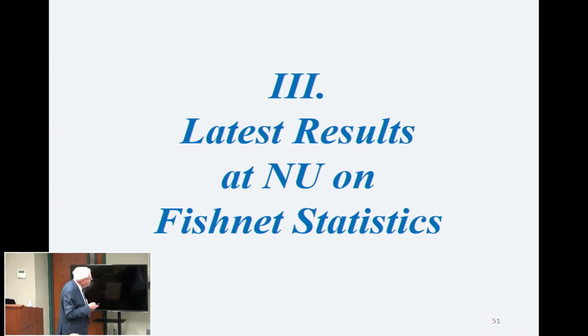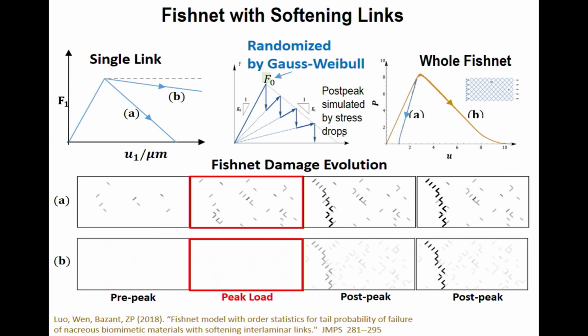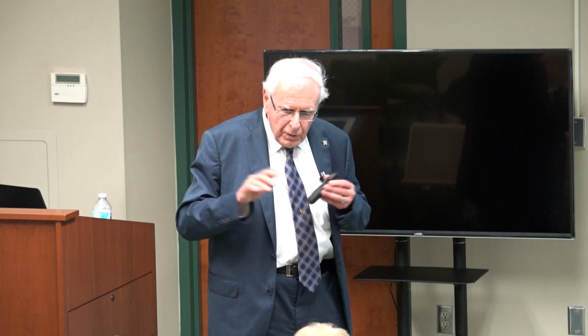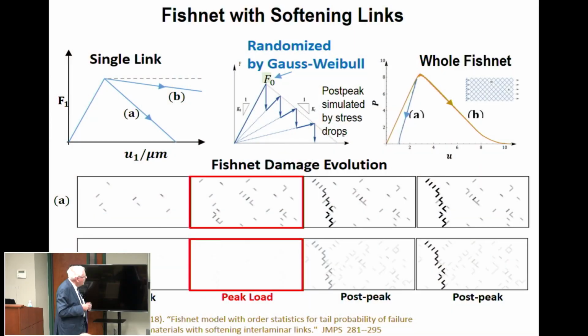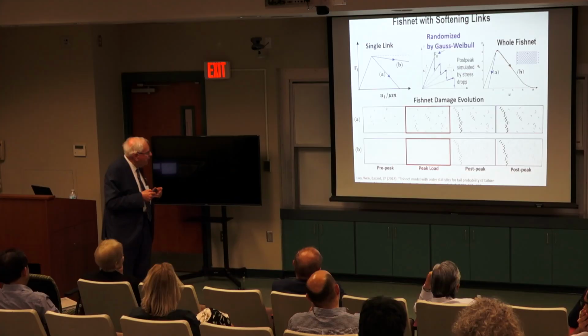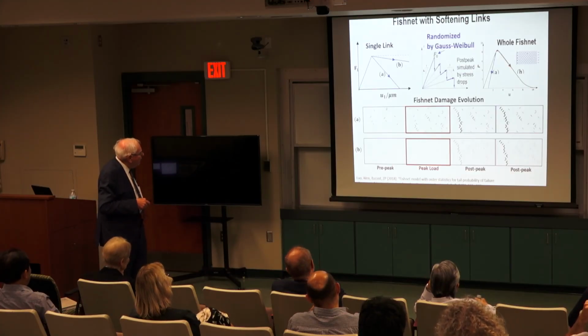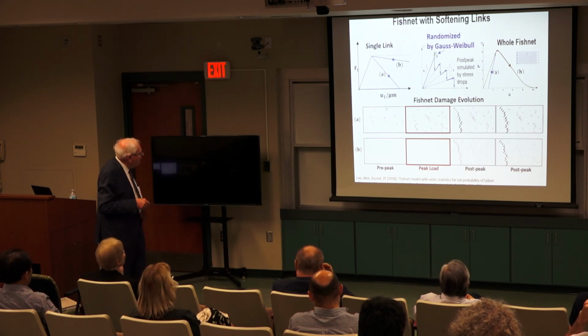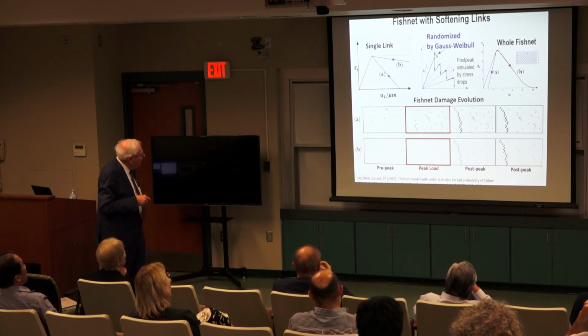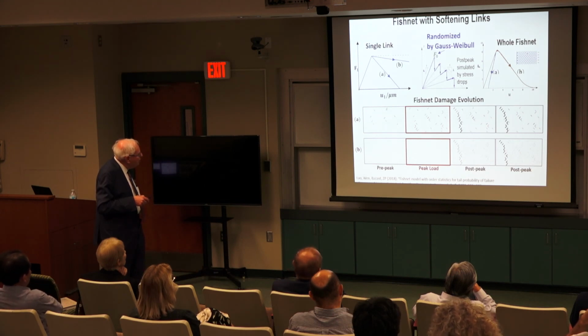Now some latest results over the last 4 months. Actually, a paper just appeared on this. Another question is, if we have this staggered platelets arrangement, I assume that the bond between these two fails as soon as the crack forms and it runs dynamically through the length of the connection between the two platelets through the biopolymer. But that's not clear. It may work in a cohesive way, that you propagate a long crack and then it becomes dynamic. And if there is a long crack, what it means in practical terms is that the transmission of force in one link is not straight down or nearly straight down, which is perfectly brittle, but gradual softening. And there can be various slopes. Eventually it can go to zero slope, which will be a plastic link.